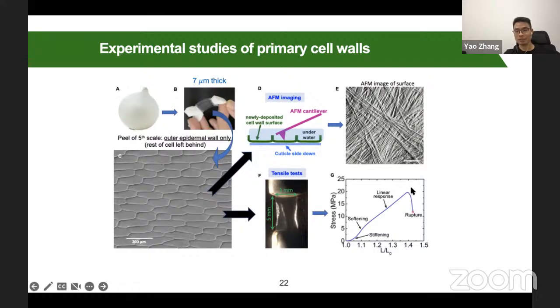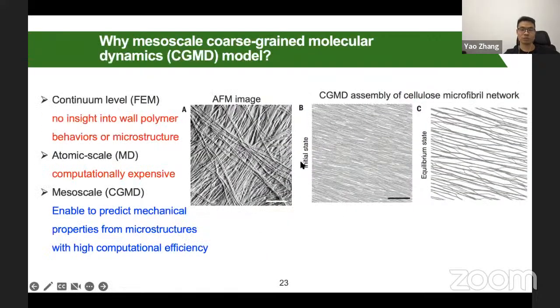Until the rupture happens, in this large strain range, you can see that the apparent modulus almost keeps constant. And this trend of the stress-strain curve is much different from other materials such as rubber and also hydrogel. They are all different. So we want to develop a model to understand the underlying mechanism, and also use the model to explain the experimental result. So we want to choose the modeling method.